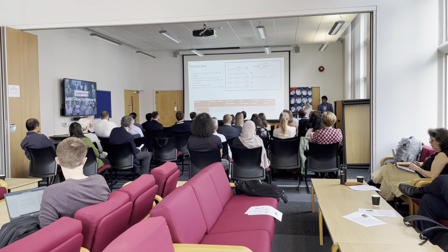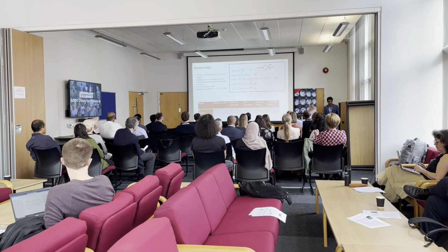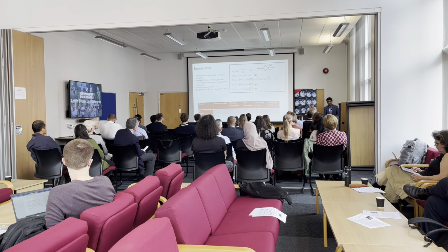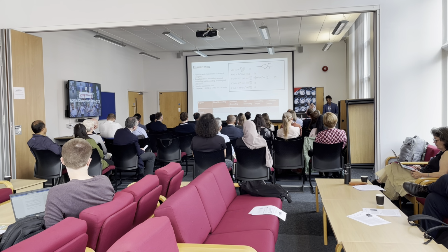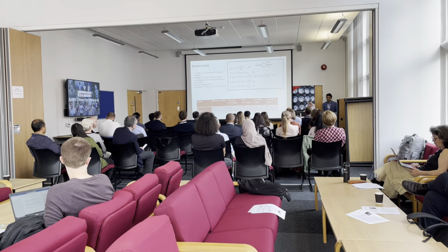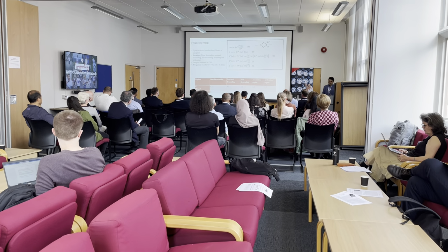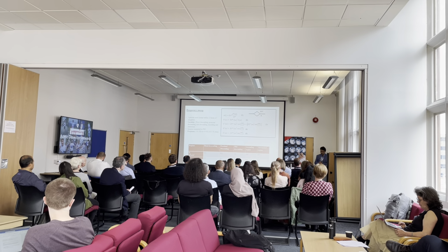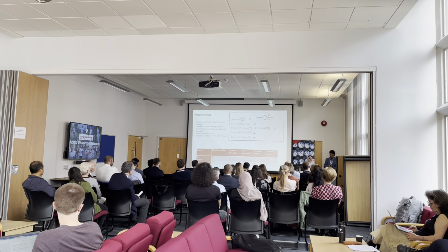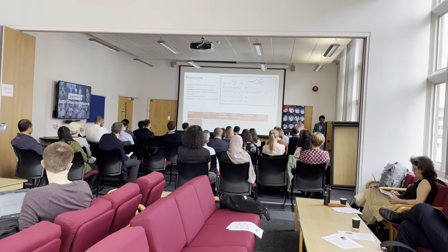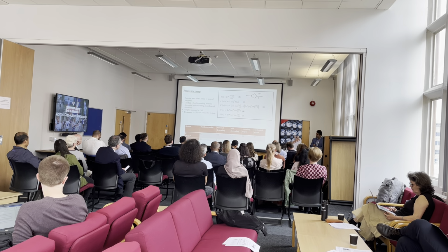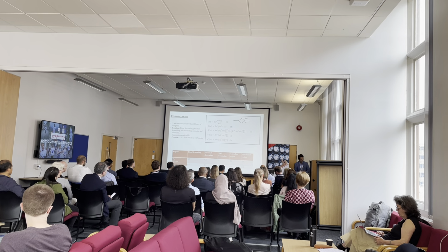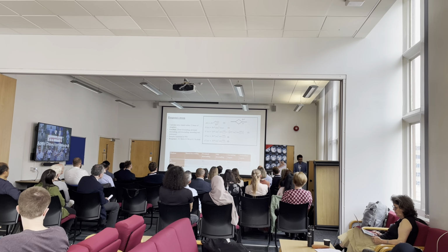So I was fitting these equations using software like MATLAB, performing some mathematical modeling there, and then extracting these parameters, which are k alpha and alpha. Now, k alpha is the coefficient of consistence, which takes into account the rate of binding and unbinding of, I would say, collagen, elastin, and the interstitium. Because as the frequency is applied, there is some binding as well as unbinding, which has been quantified using this parameter known as k alpha.